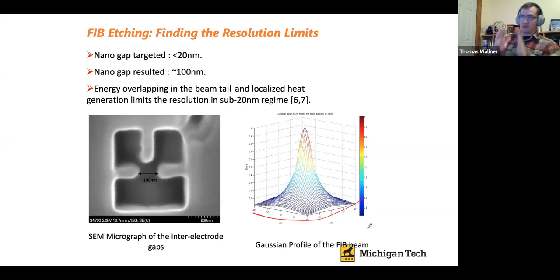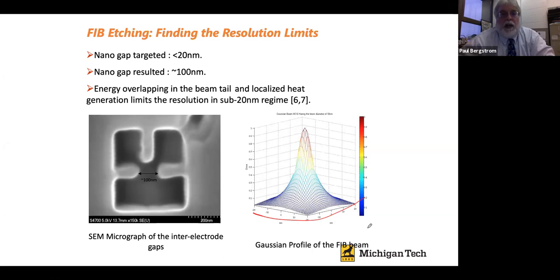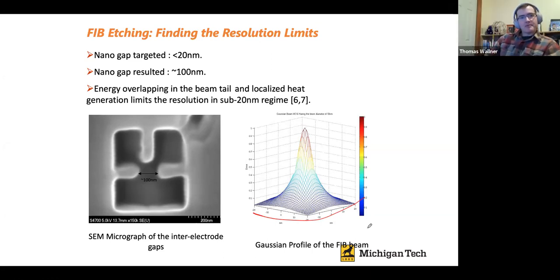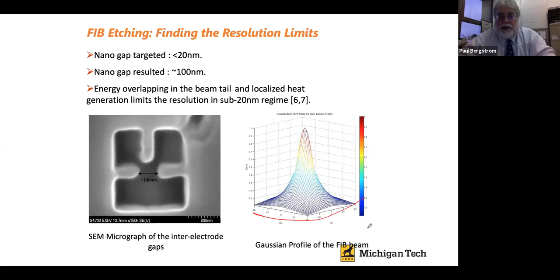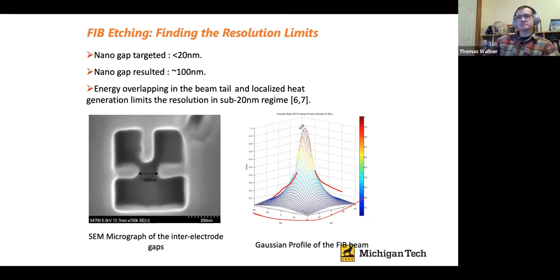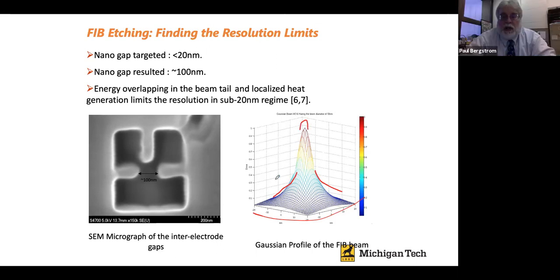Is there such a thing as sharpening that tip a little bit more? Like, could you go buy a sharper pencil? To an extent, regardless of the focus. So the answer is yes and no. It is possible to produce finer featured ion beams, but even if they are finer featured, they still have this Gaussian tail that is still transmitting energy in an area that's much larger than the tip. Even if your focused energy is very small, there's still an appreciable, roughly half the total energy, transmitted over a much larger area.